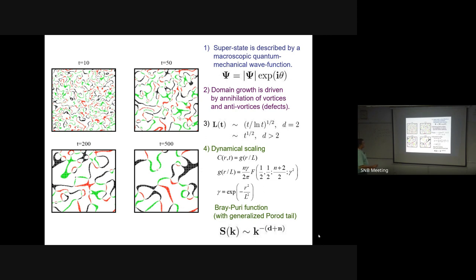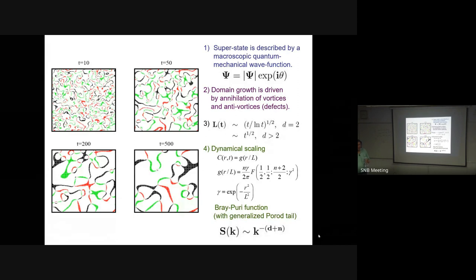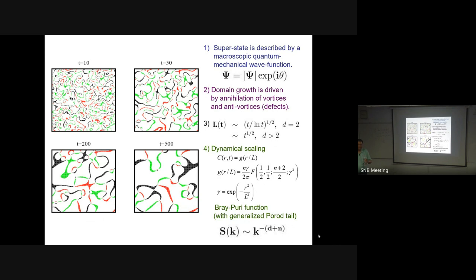This complex wave function is described by the dynamical XY model. In the DDGL equation, ψ now becomes a two-component vector - the real and imaginary parts of the wave function. This is not one order parameter but two. The amplitude is fixed far from vortex cores, but at the core of these vortices the amplitude actually goes to zero - exactly the same paradigm as earlier where interfaces were the points where the order parameter became zero.